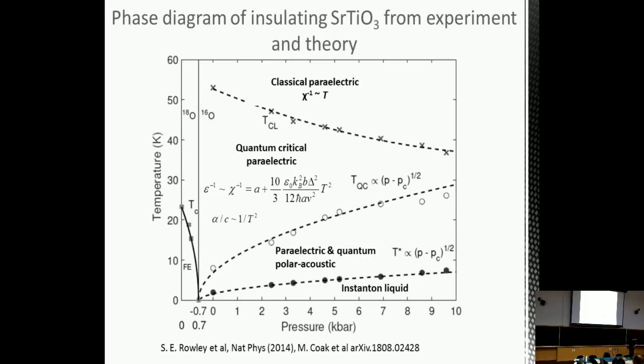So here is a more detailed phase diagram for strontium titanate, which has now been mapped out by Coak and co-workers in Cambridge. And we see here suppression of the ferroelectric transition, a large quantum critical regime where you have a quadratic form of the inverse susceptibility, and also a divergence of the Grüneisen parameter, which we've measured here, which is very unusual in an insulator. And then below this line you have a deviation away from the T-squared because there's a gap in the transverse optic phonon spectrum in this part of the phase diagram.